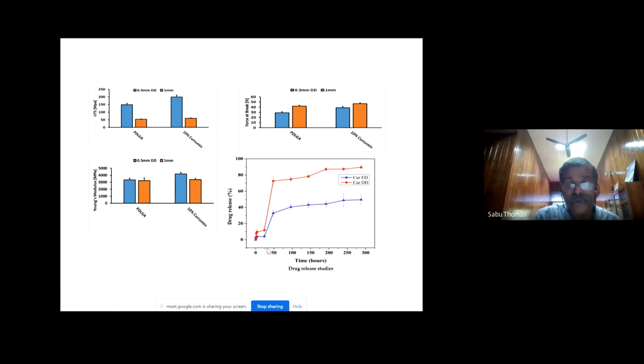Now look at the drug release. We introduce drug into this fibrous structure, the suture, because when you do the suturing process, we also introduce a drug. You look at the drug release as a function of time. You will find that these are all compounded with the curcumin. The difference is the top, the red one, is the drawn material, the drawn fiber, less diameter. You see, the drug release is much faster. The drug has to be released at a faster rate. This is the extruded material. The blue one is extruded without any drawing process.